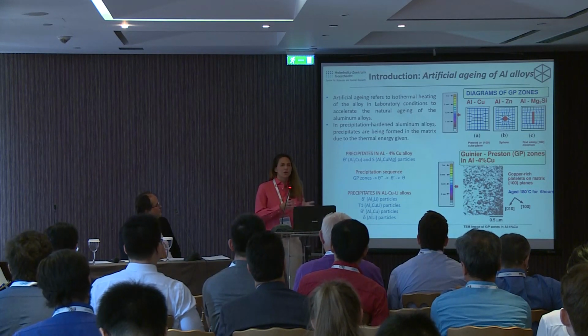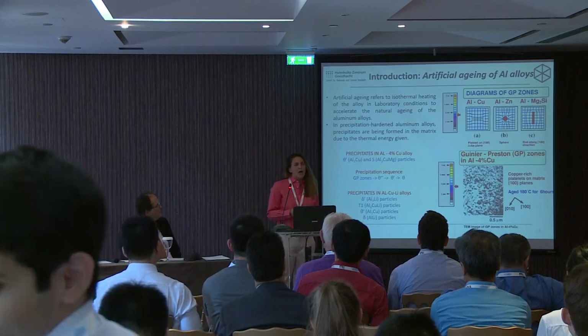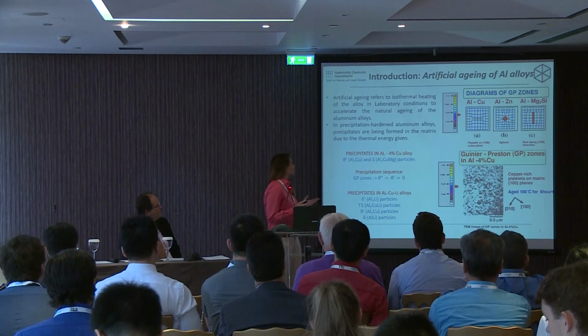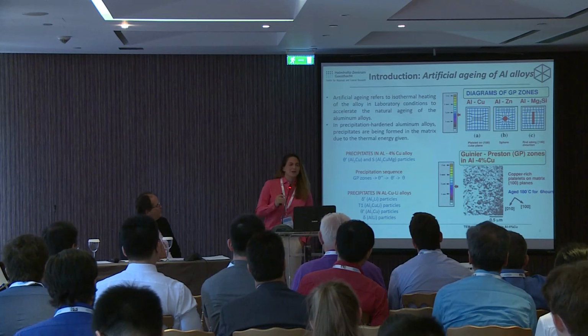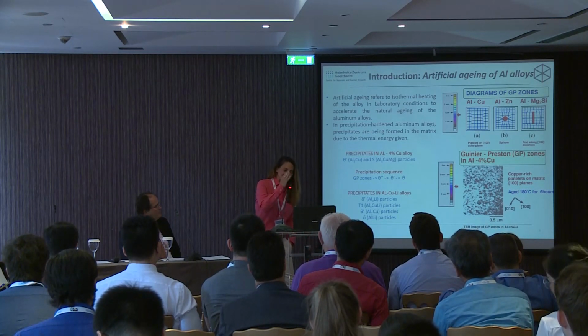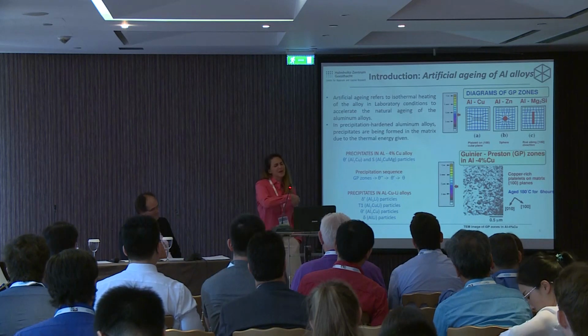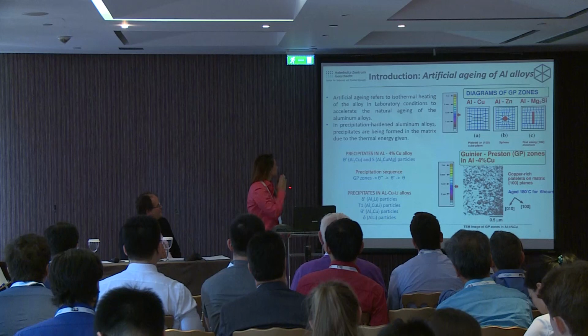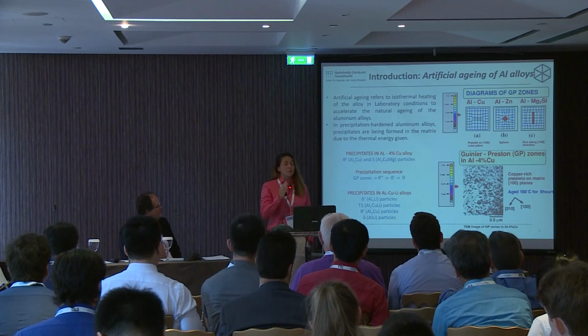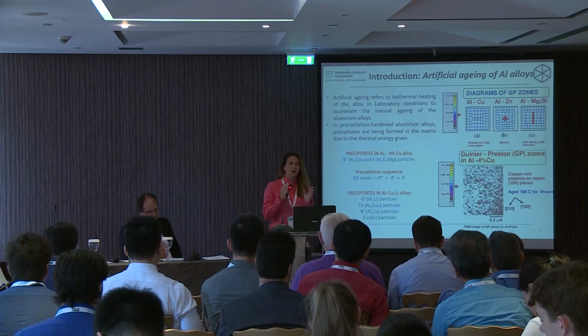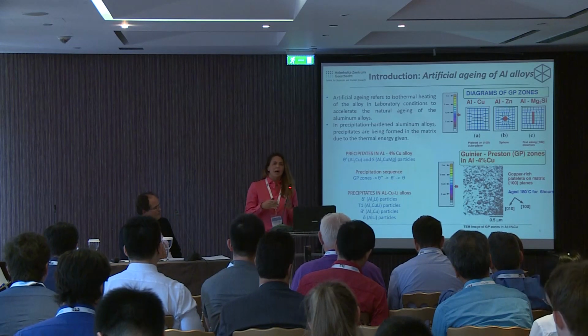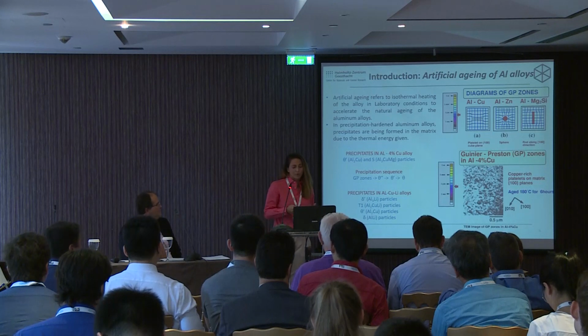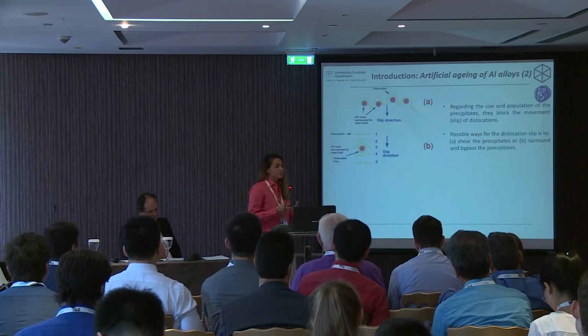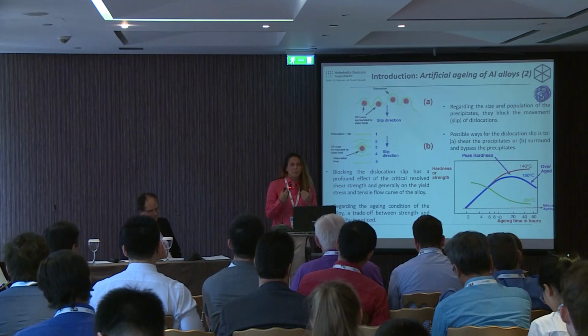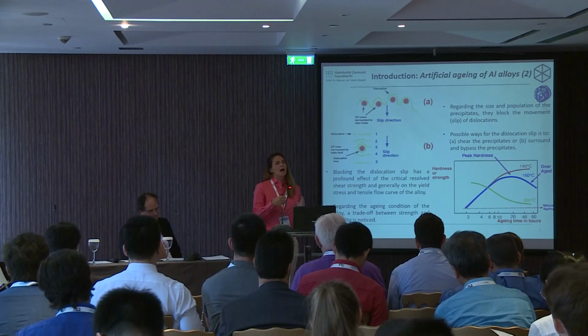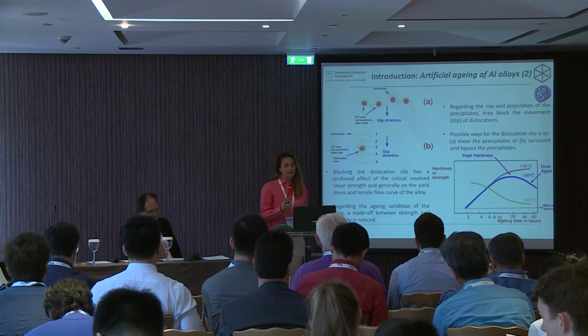By this I mean that with natural aging or with artificial aging, you can tailor the properties. For example, for this alloy, you don't have only one mechanism, but you have 4 different. That makes the situation more difficult. But why do we need these precipitates? Because they are blocking the dislocations. By blocking the dislocations, you can increase yield strength, and you sacrifice ductility.